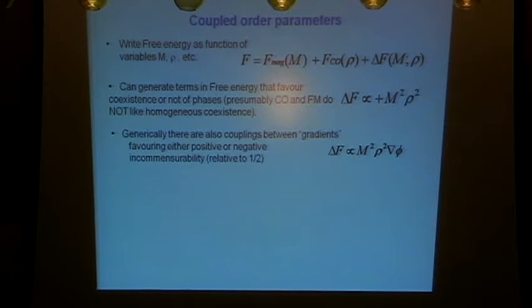The fact that such a linear gradient term is allowed by symmetry just means that stretching the chain and compressing the chain do not give rise to the same state. So in the absence of particle-hole symmetry, in general, we don't have that here. This term is there. I don't know what the sign of the coefficient is, but it doesn't matter. It actually has profound effects. It's a term which couples to gradients. So you remember that I originally had a term in my free energy for the charge order, which was grad phi minus q. So a term which is like this is like shifting the q vector from the one you expected it to be to something which would then depend on this coefficient, which actually depends on M squared.